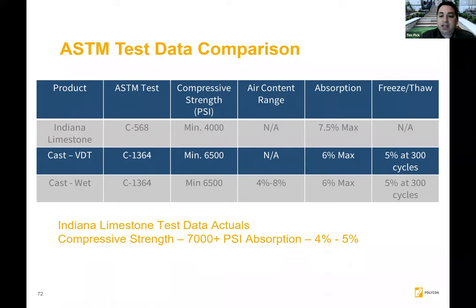We have Indiana limestone throughout Canada, so we know it works in our environment. We have quite a bit in Alberta where we have lots of freeze-thaw. We even have a project in Quebec where we used it as a thin, lightweight limestone panel on a cell phone building where there's fans inside that are heat extractors. So it's using the vent screen on it. During the winter, those fans turn on every half an hour. So that stone goes from freezing to hot every 30 minutes in the wintertime, and no issues with breaking it at all.